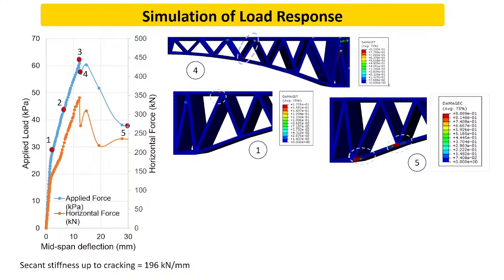And here again, we're cheating a little bit, because we've only done the linear calibration, but we're pushing our simulations to see what load the bridge could actually take. So here is the load response that we got. That's the curve in the blue. And we see that it actually goes to a pretty high stress, the pressure that can be applied. It goes to about 64 kilopascals or so. That is the pressure that can be taken before serious damage starts to happen.